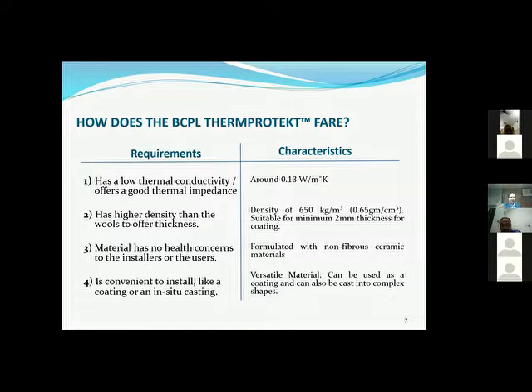I'll restate that because I missed it. The density is 0.65 gram per cc, or 650 kilogram per cubic meter. Your general blanket is in the range of 128 to 164 to 220. So this is almost 3.5 to 4 times heavier than the wool. But for that heaviness, you still have a very low thermal conductivity. That trade-off is somewhere matched out, because you would get a lower thickness of coating. You can start out with 2 mm thickness as well. Now, health concern wise, this specific formulation is formulated without the use of any fibrous materials. There is no fibrous material that has gone into the formulation of ThermProtekt.